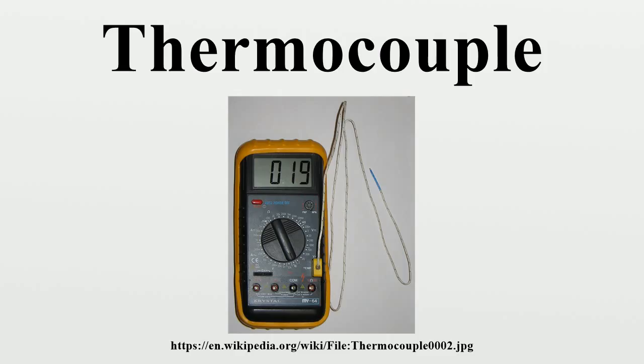If the aged section of the thermocouple circuit is exposed to a temperature gradient, the measured voltage will differ, resulting in error. Aged thermocouples are only partly modified, for example being unaffected in the parts outside the furnace. For this reason, aged thermocouples cannot be taken out of their installed location and recalibrated in a bath or test furnace to determine error. This also explains why error can sometimes be observed when an aged thermocouple is pulled partly out of a furnace, as the sensor is pulled back.